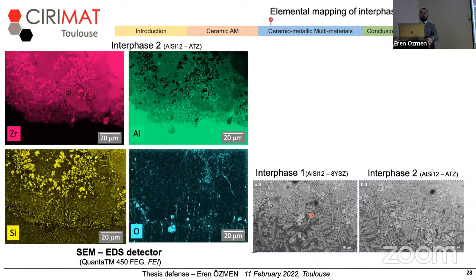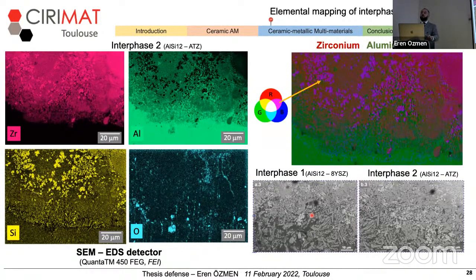So to check what those microstructures are and what the elemental distribution in these microstructures is, I again ran an elemental mapping on these microstructures. And I checked 4 different elements coming from the ceramic and the metallic part. So before overlapping these elements, I had to change silicon from yellow to blue because yellow is also a mixed color. So to prevent confusion, I had to identify it with blue.